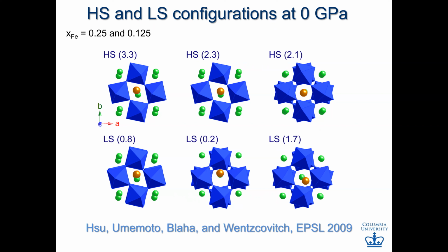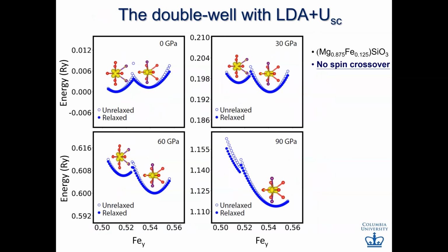And the low spin state has a quadrupole splitting that's pretty small. So this is what's happening with iron. At low pressure, the low quadrupole splitting iron has the minority electron in the XZ orbital. And there is the other kind of iron, with the high spin, with the minority electron entering a different orbital. So there is a change in the electronic configuration of iron under pressure, where the minority electron jumps from one orbital to another, but this is not a change in spin state.